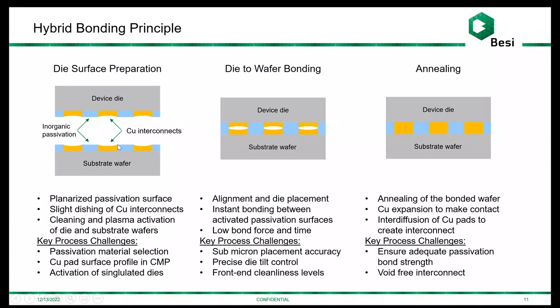So we have to have almost perfectly flat structures there. And in addition, we need to have the copper ever so slightly recessed below the surface of the passivation so that we can make the first contact during bonding between the passivation layers and not between copper layers. That's called dishing. You might hear this word dishing. So once we achieve that very flat surface and the dished copper, then we have to activate the surface. For this, we're typically using some kind of a plasma to create an activated oxide surface so that we have an attraction when these two surfaces meet and kind of a spontaneous bonding.